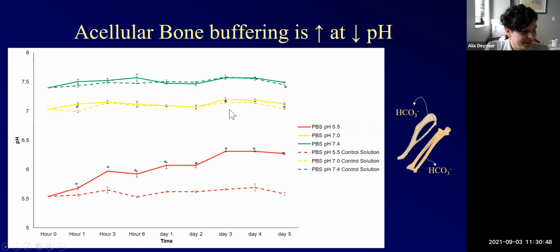Even at 7, after about 3 days, I start to see significant changes where we are successfully buffering and raising the pH beyond 7. At 7.4, it's not really doing much, but that's kind of normal because bones are used to being in 7.4. So, phew, okay, all is well. But we can confirm that indeed, when you put a bone into a solution of an acidic body fluid, pseudo body fluid, you are releasing some sort of buffering moiety. So great, this is representative of in vivo, very good.